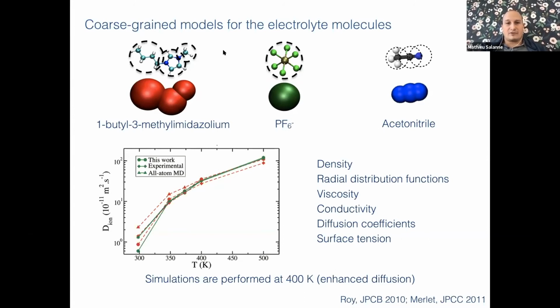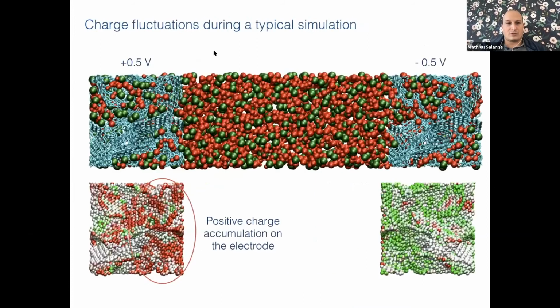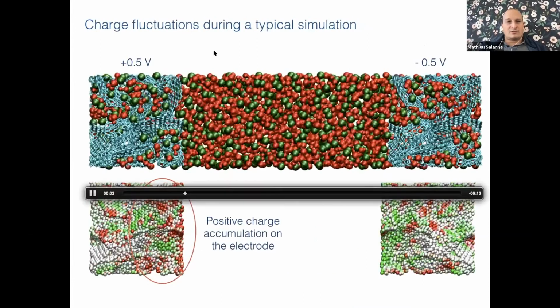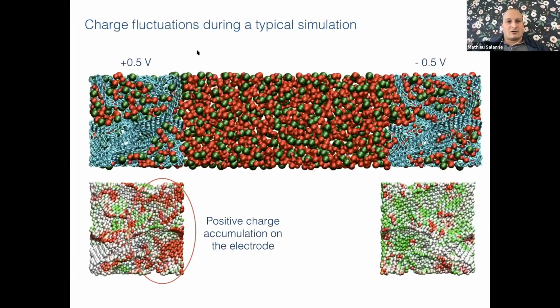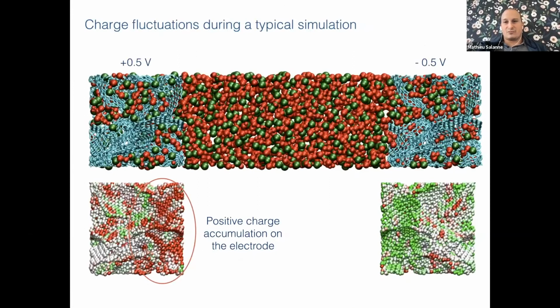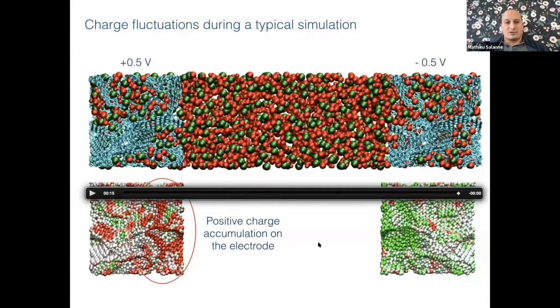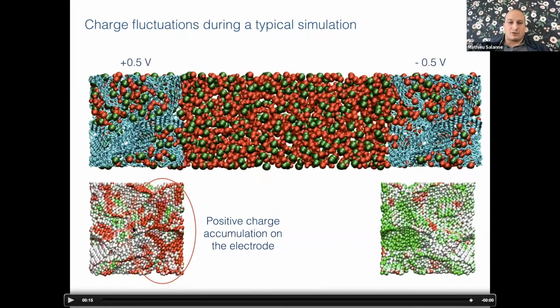And so here you have an example of the first simulations we were doing, more than 5 years ago, where we apply a voltage between the two electrodes, and you see, well, it's not so easy to see, but over long time scales, there will be an accumulation of anions. These are the green spheres on the left, and accumulations of cations on the right. And at the bottom, the second movie was showing how the charge fluctuates inside the electrode. So you see that when we have a red region, it means that we have accumulated some positive charge. On the contrary, a green region means accumulated negative charge. And so progressively, we will charge these electrodes. So this is really consistent with what is done in experiments.